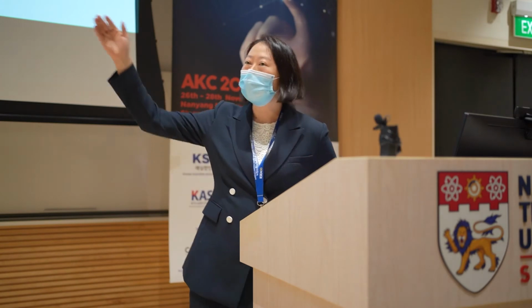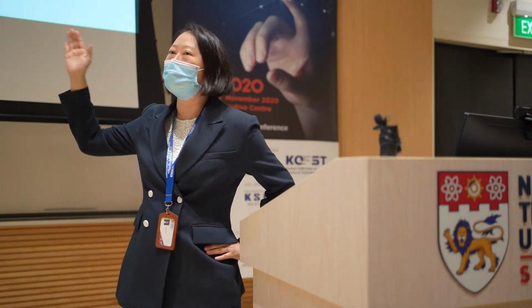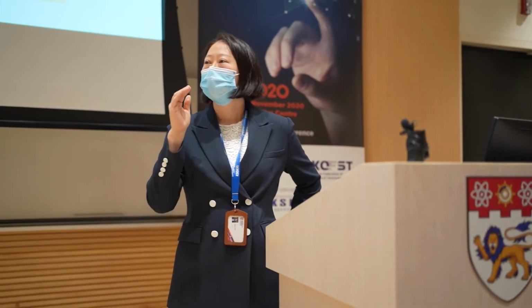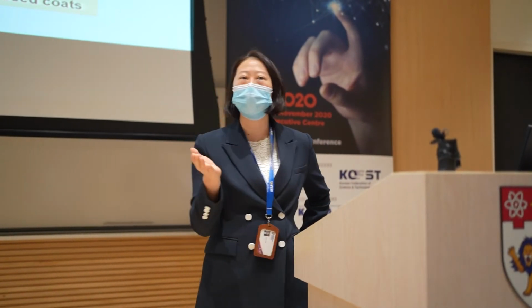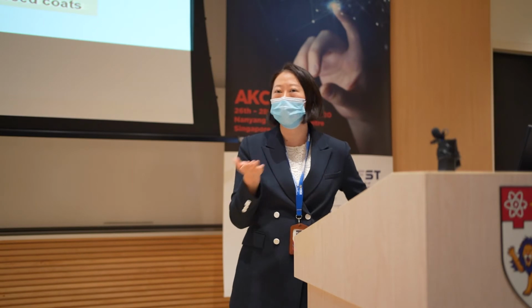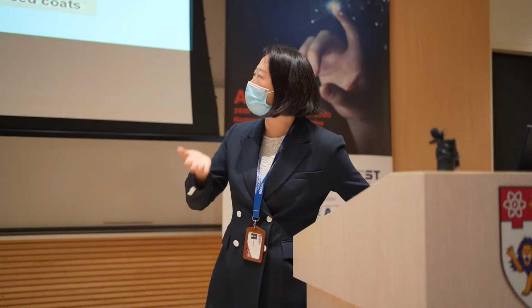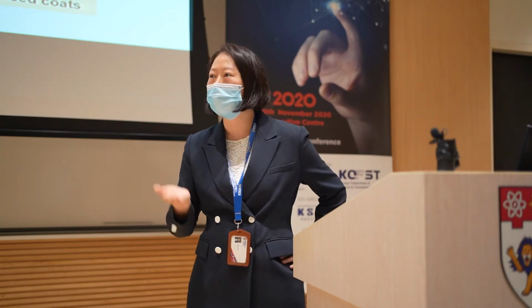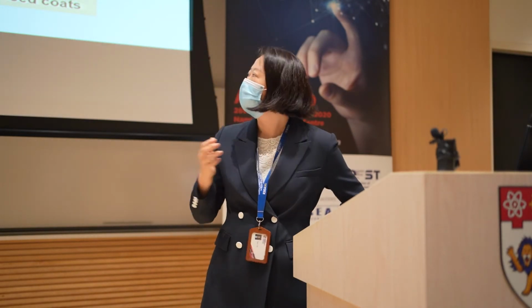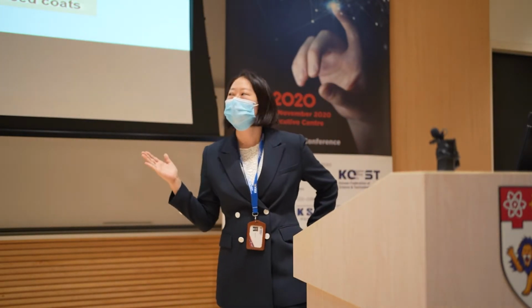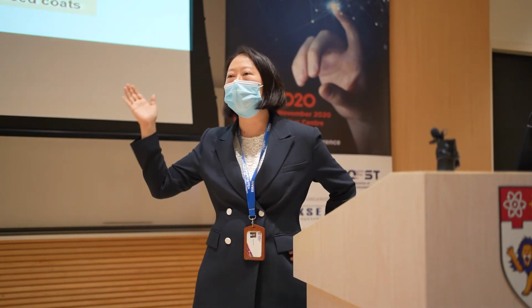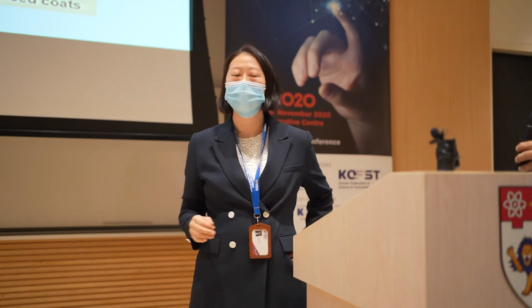Second, when you do 3D printing, a lot of techniques are involved, especially to make the material from liquid to solid, because your material needs to be solid after printing, otherwise you cannot use it. Then during this solidification process, your cells also die because they're exposed to UV damage or chemical toxicity, or sometimes humidity or temperature changes. Because of that, as a result, you can kill the cell.